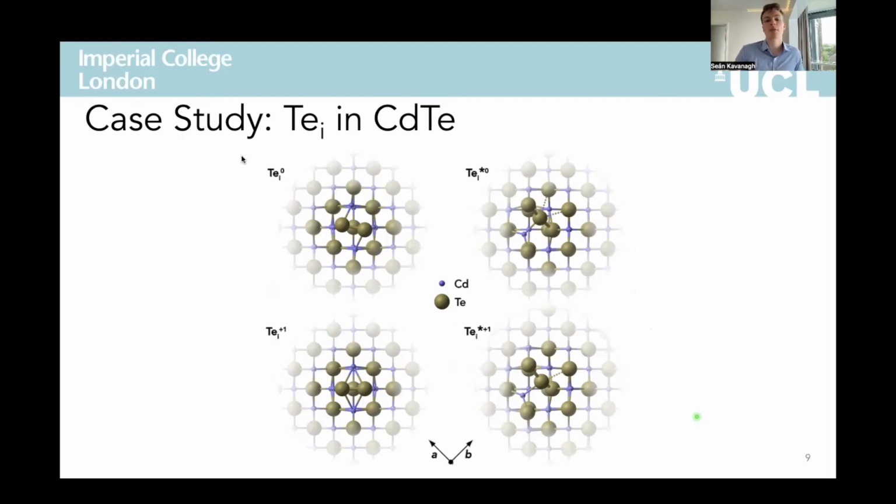Tellurium interstitials have low energy metastable states for both the neutral and the +1 states. So in the ground state arrangement, tellurium interstitials adopt this split interstitial dimer arrangement, directed along the 110 direction in the +1 state and then slightly twisted about this axis in the neutral state.